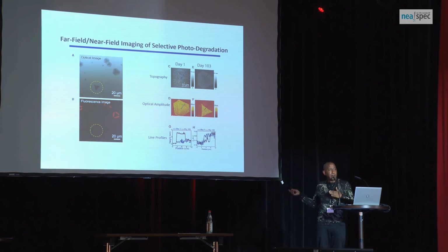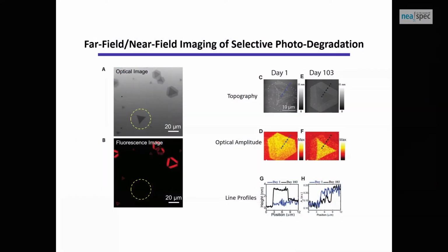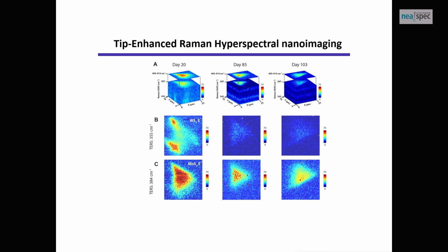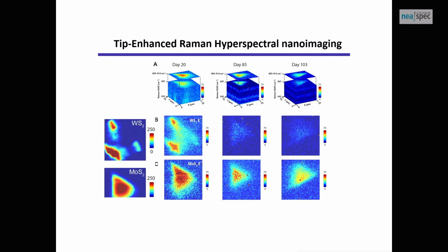But at the end of the day, after several days, when WS2 has degraded, you can see that the outer layer is almost similar to the substrate, which is SiO2. It's completely oxidized. So you can measure that number as well in this way. The other thing you could do is you can also take Raman, tip-enhanced Raman, and also compare structural information with the PL emission with this technique. So we did that, and the result, as you can expect, is similar to that of the PL. Wherever you have more WS2, you have more emission. So it kind of correlates with our PL measurement.